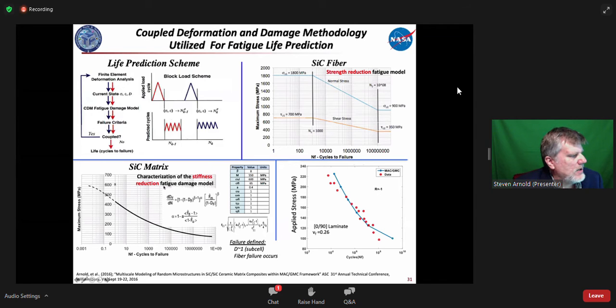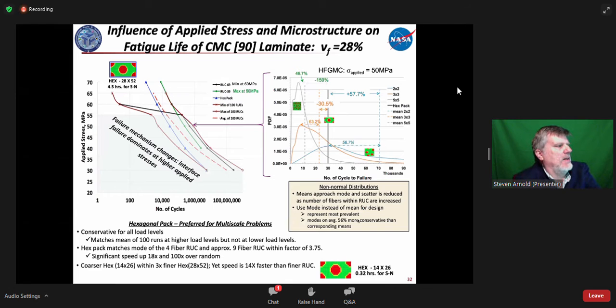And then we also do a stiffness reduction of the matrix, and combining these two, we're able to reasonably accurately predict the S-N curve here for a 0/90 laminate at temperature. And then even more interesting is that we can actually go in, and we've done that, looked at the effect of microstructure on fatigue curves. Here we're showing a 90, which obviously is the most severe effect of the microstructure under transverse loading. And we're showing that here we can calculate the full S-N curve.